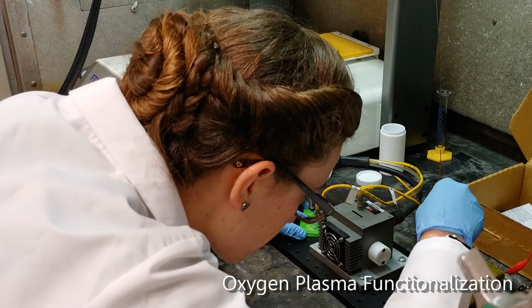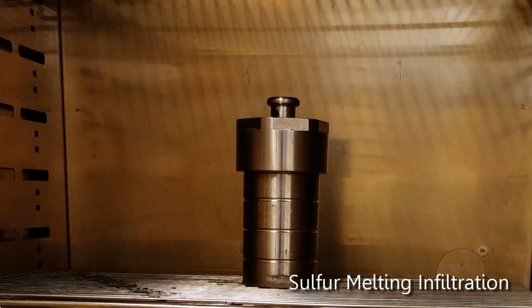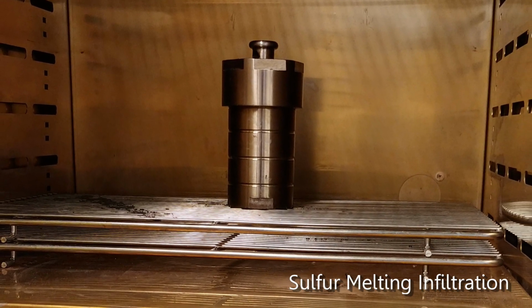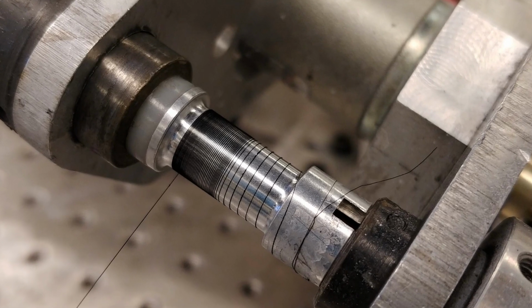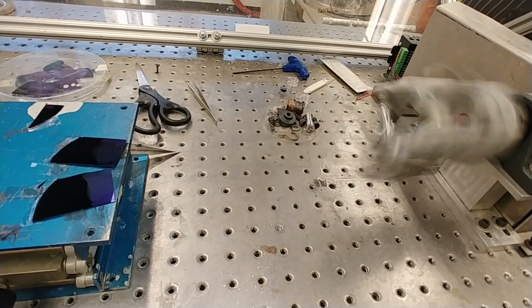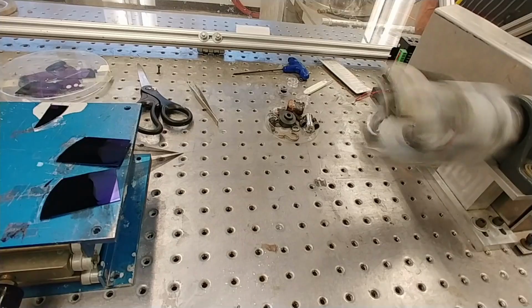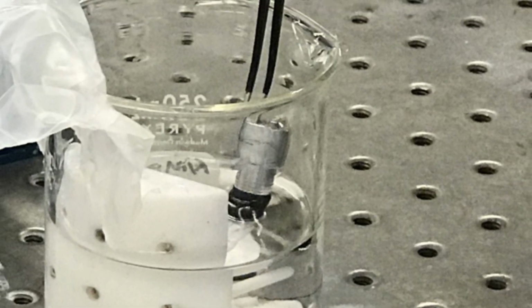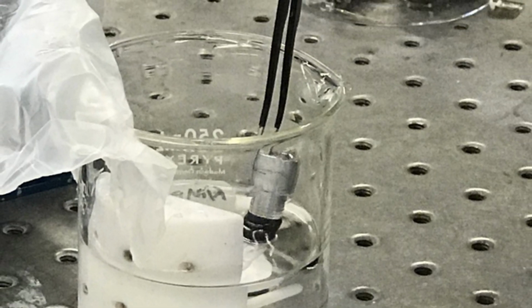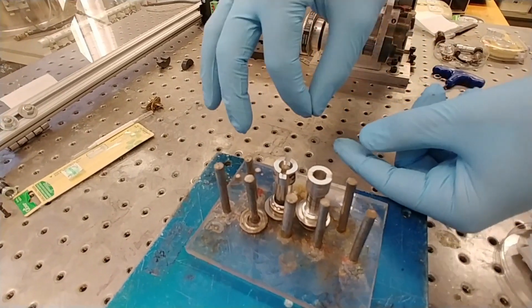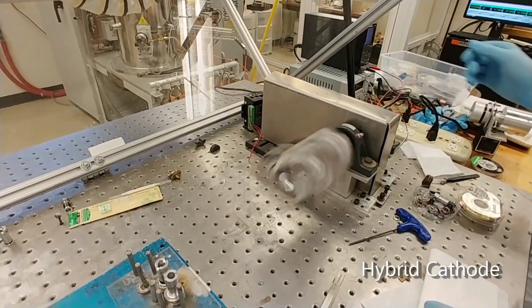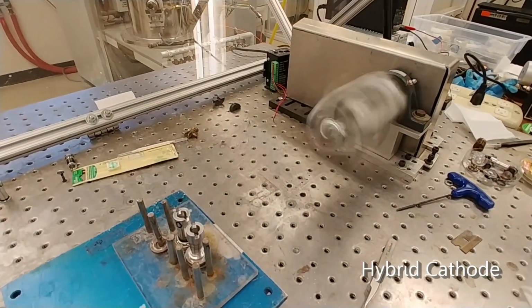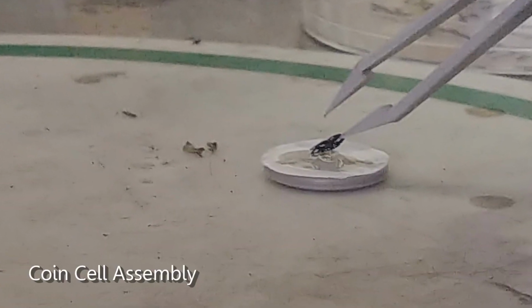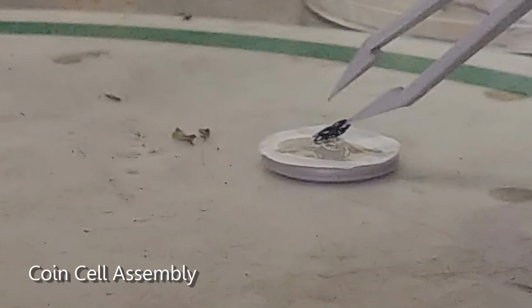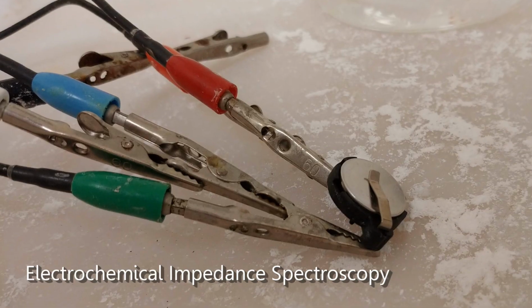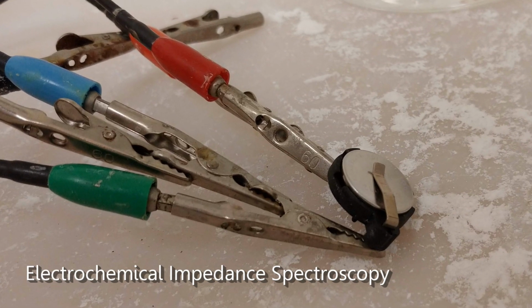the threads to oxygen plasma, and used a sulfur melting infiltration process to add the sulfur to the carbon nanotube thread. The other part of the hybrid thread is composed of a carbon nanotube thread which was exposed to acetone, creating a densified thread. This densified thread was combined with the sulfur-loaded thread to create our hybrid cathode. To test the conductivity, the hybrid cathode was used in a coin cell battery and tested with electrochemical impedance spectroscopy.